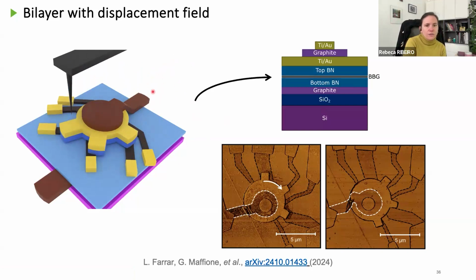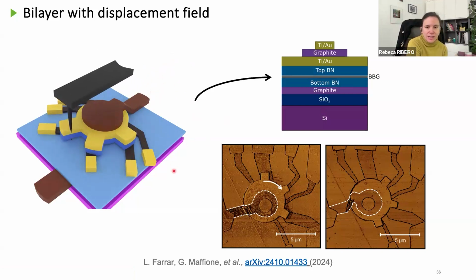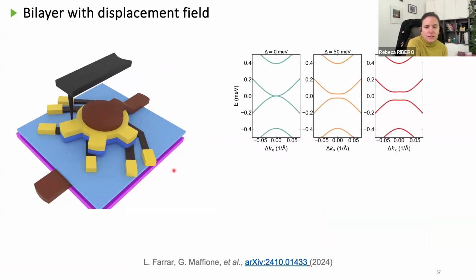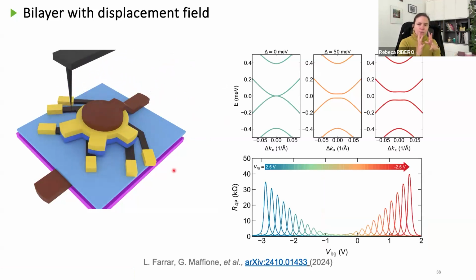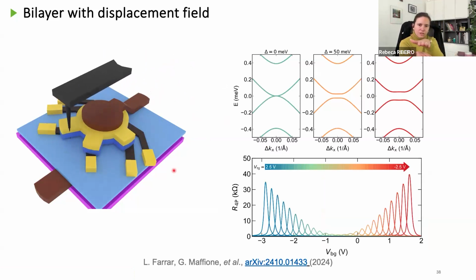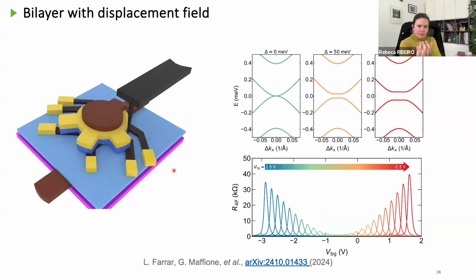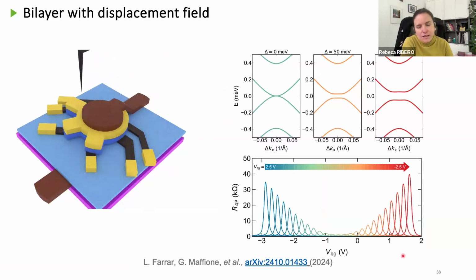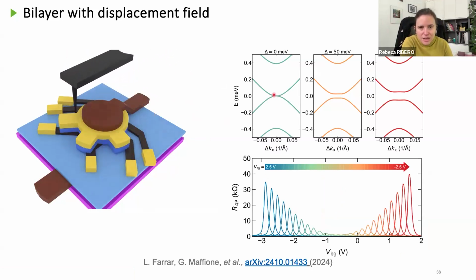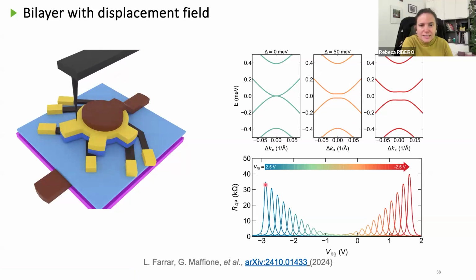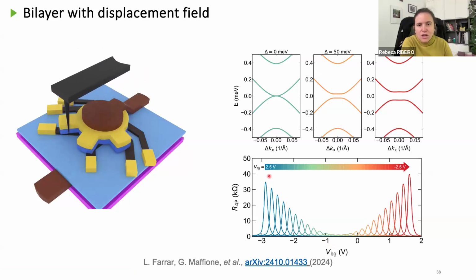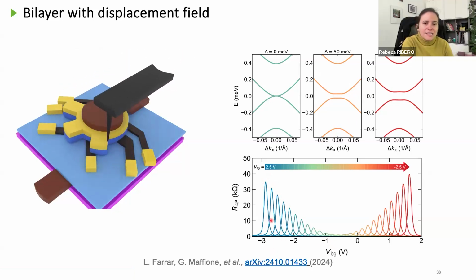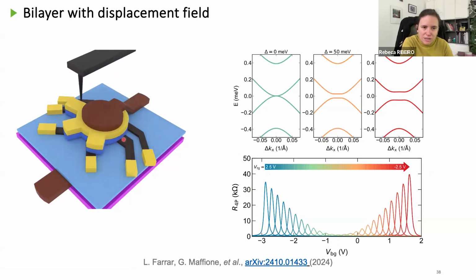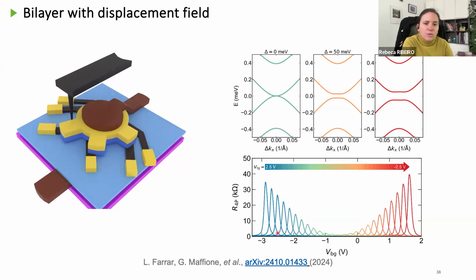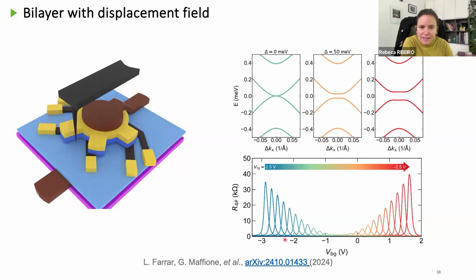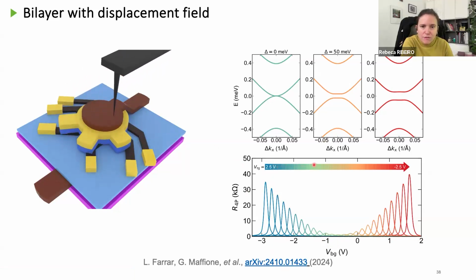So how do we know if these top gates work? Well, bilayer graphene has this property that when you apply a displacement field, you can open an energy gap on it. What happens when you open this energy gap at the charge neutrality point is that your resistance will strongly increase. So here we have the example of one of these devices where we are changing the back gate for different values of the top gate.